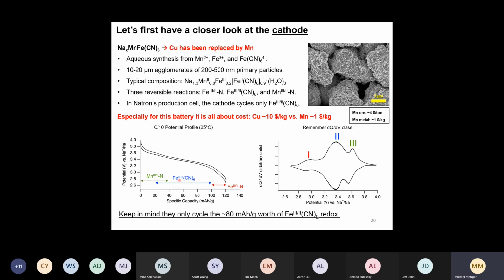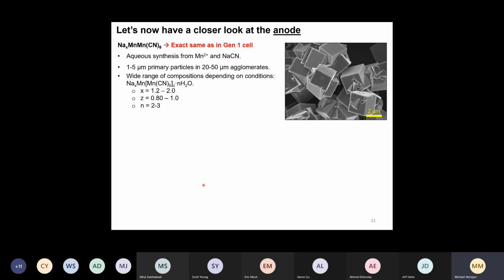And they used the iron 2+/3+ redox of the iron that is bound to the carbon atoms, which gives you about 80 milliamp hours per gram. So now let's talk about the anode. This is something we did not discuss yet. First of all, it's a beautiful structure, in my opinion, which you can see here on the right-hand side. Truly cubic crystals, right? And this anode that they are using in their second generation cell is exactly the same composition as the anode in the first generation cell.